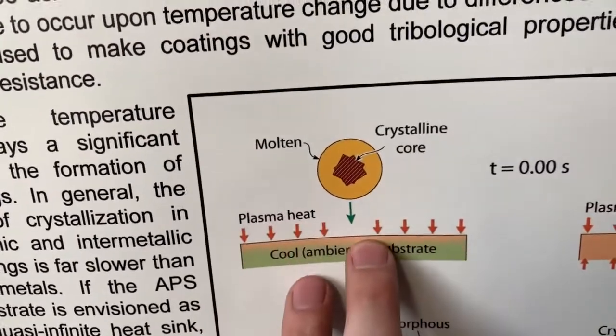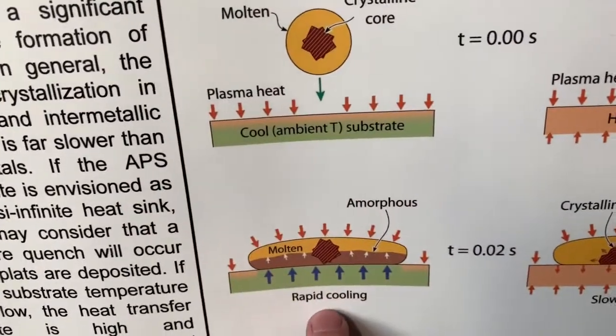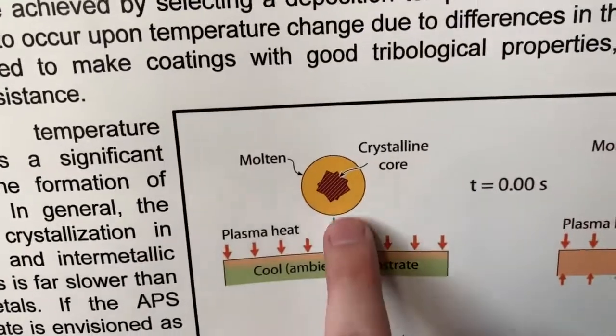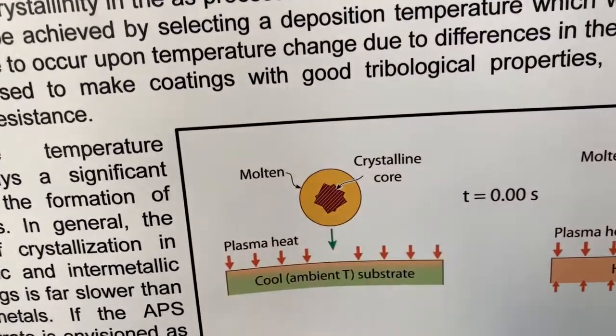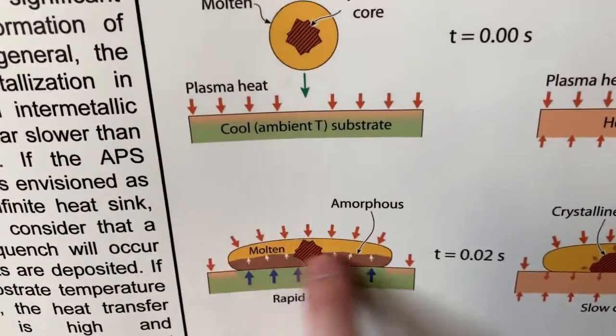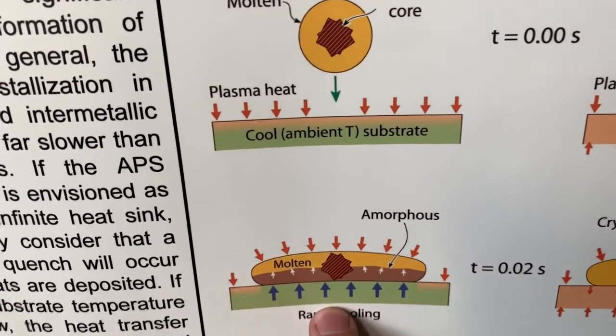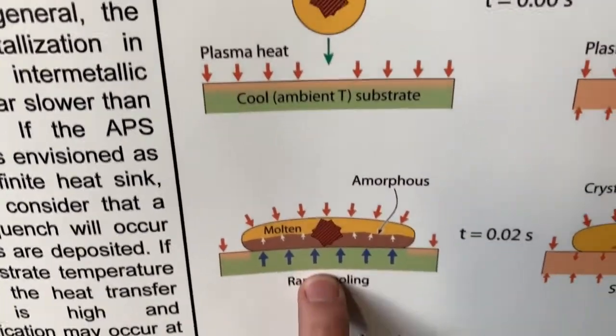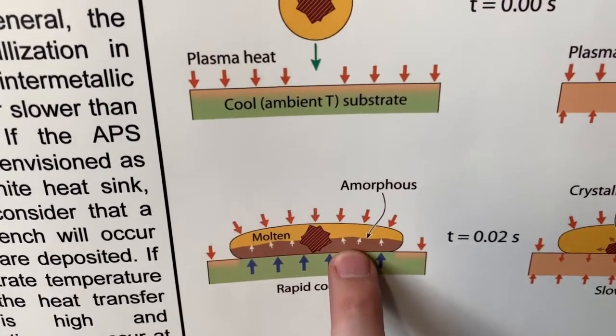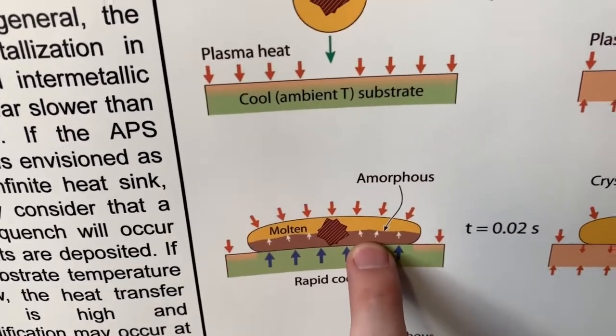Then when that particle hits your material, you're starting to get rapid cooling. Now this material, because it's shot at a high speed, it will actually form kind of a splat like this. And because you have rapid cooling, you will actually start to get some amorphous material growth. It will not have the time to actually form a crystalline material.